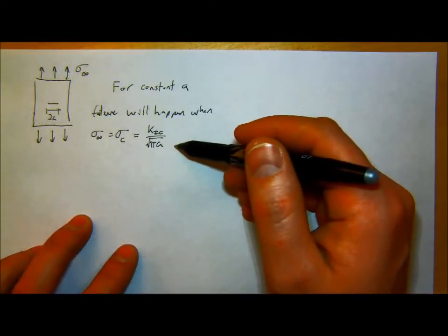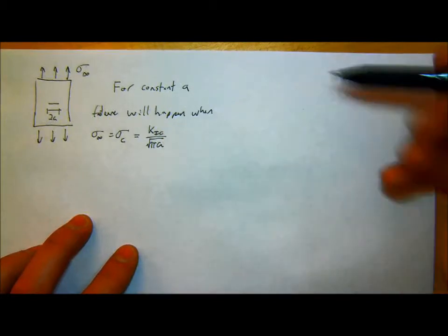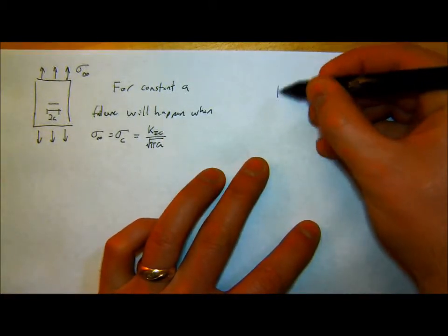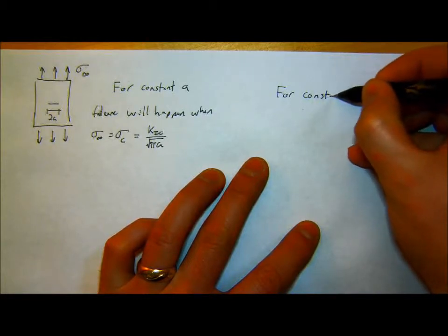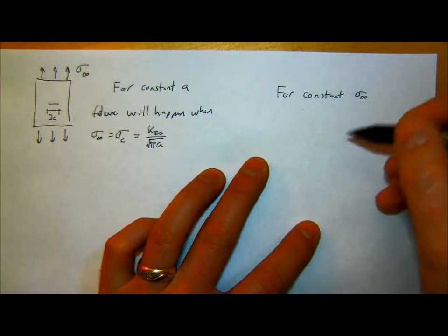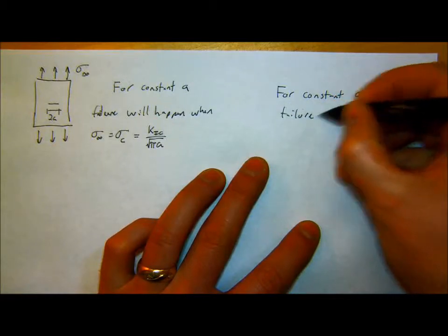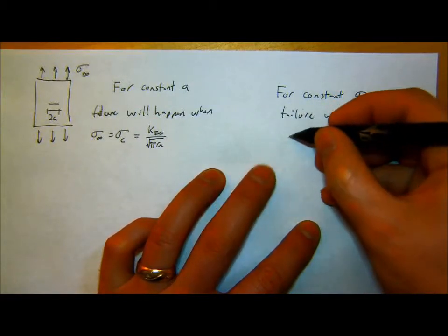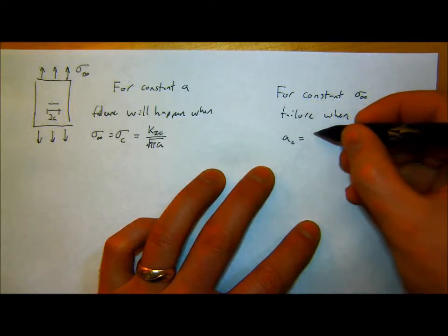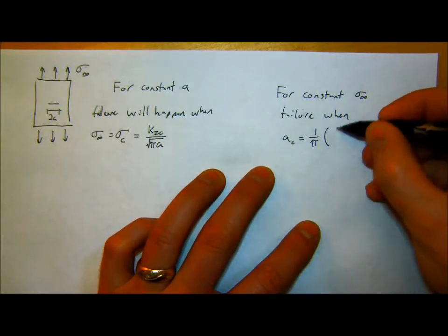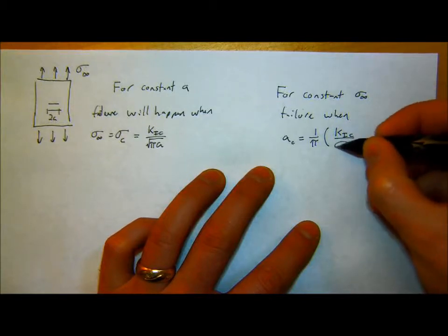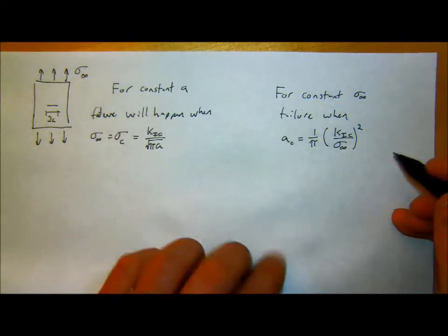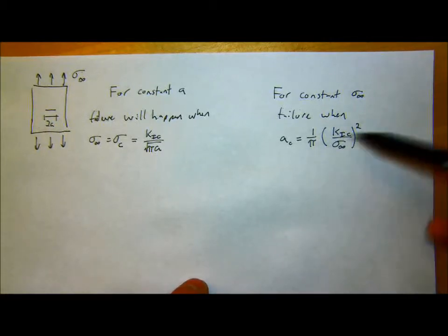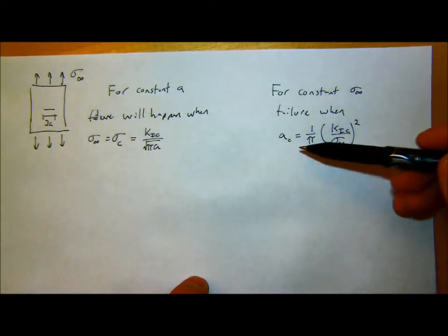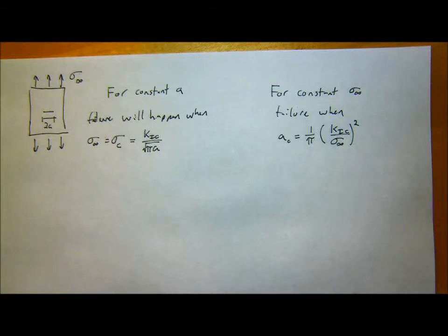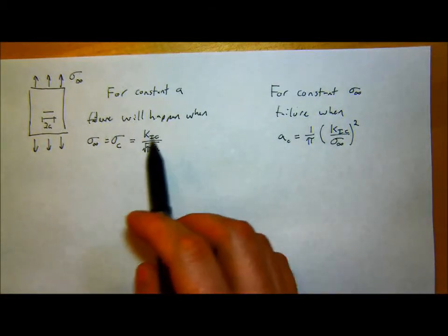For a constant given applied stress, failure will happen when a critical is equal to 1 over pi times K1C over sigma infinity, squared. So if I apply a certain stress, this is how big of a flaw I can have before my material will break. And that K1C varies material to material, and this sets the limit of how big of a flaw I can have for a certain material size, or how much stress I can apply.